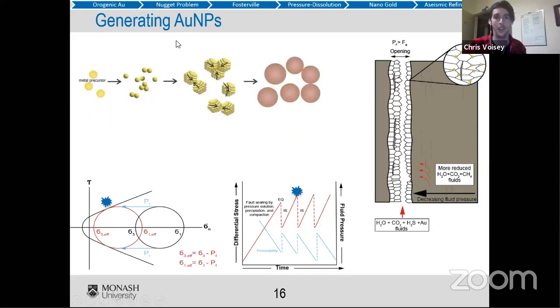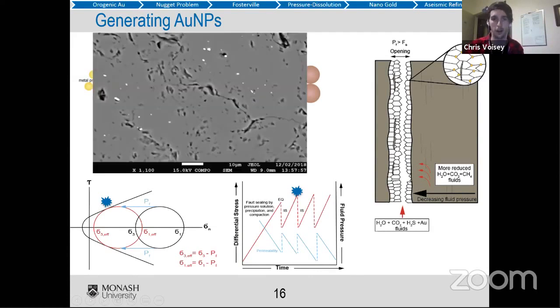So this is what the aggregation looks like. You have a few little metal precursor atoms, they smack together, they can then grow, and then you build modest sized nanoparticles. And this is what it would look like in your sample. So we have a quartz vein here, a couple of quartz grains in it, and there's gold trapped in it. No particular looking suspicious chemical trap or physical trap. It's just locked into a quartz vein.